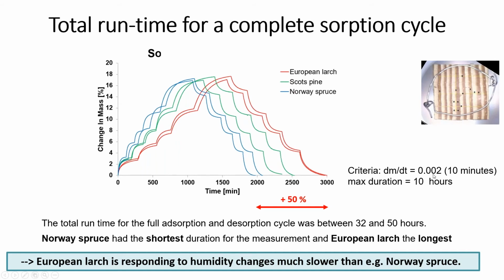So Raphaela set up a criteria, mass over time, for 10 minutes. When that is reached, it jumps to the next step, to the next humidity level. But she let the time, because the time is limited, I think by standard 360 minutes. I might be wrong, but we extended that to 10 hours. So we really gave the machine the option to get the equilibrium.